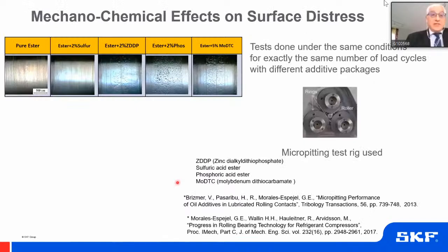Now, something important to say is that this failure mode depends pretty much on the lubricant that you have in your system. And this is just an experiment that has been published in this paper with my colleagues here, where we have used this micropitting tester that has 3 rings and 1 roller in the middle. So we try to induce the micropitting or the surface distress in the roller.